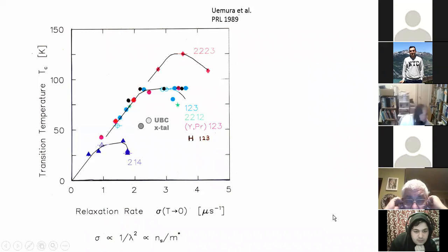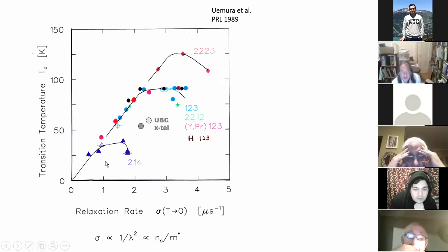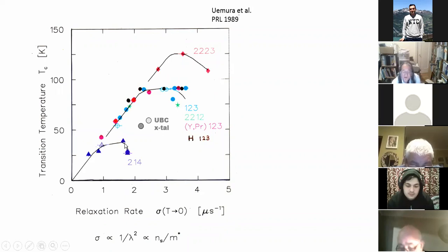Soon after the discovery of these cuprate superconductors, we performed this experiment in many different specimens of copper oxide superconductors. The transition temperature of the copper oxide superconductors can be tuned or changed by changing the carrier density, which is achieved by putting in a slightly different chemical composition. And then you will be able to see how we can measure the transition temperature TC, and how it is related to the value of this damping rate at very low temperature. The horizontal axis is representing the superconducting carrier density divided by the mass. And these are each different specimens with slightly different chemical compositions.